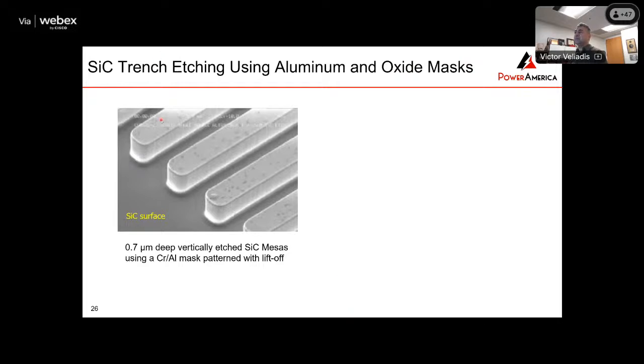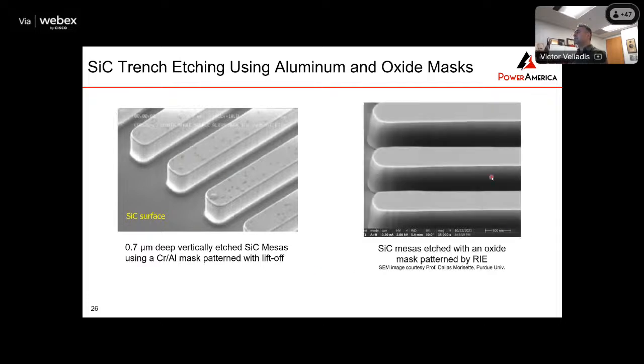And this is an example of a trench surface. This is something that I trenched in the mid 2000s, and you can see the silicon carbide pillars. And I used an aluminum mask, and the aluminum mask protected this area, so I was able to make these trenches right here. So this is an example using a chrome aluminum mask, and this is an example right here from Purdue University where an oxide mask was used to do the trenches.